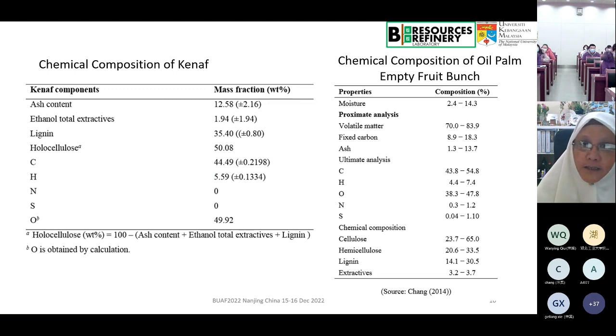So back to the kenaf and palm oil empty fruit bunch. The chemical compositions, as far as kenaf is concerned, you will notice that the lignin is quite high. It's about 35% lignin, with the holocellulose about 50%. Holocellulose is the content of cellulose and hemicellulose. In oil palm empty fruit bunch, the lignin is about 15 to 30%, depending on which part of that particular fiber is taken, and the hemicellulose is quite high, with the cellulose from as low as 23 to as high as 65.